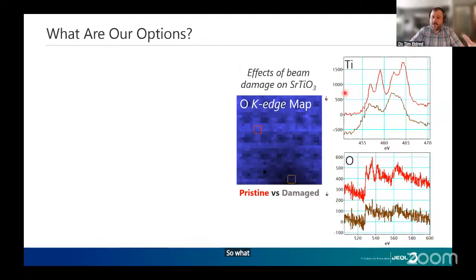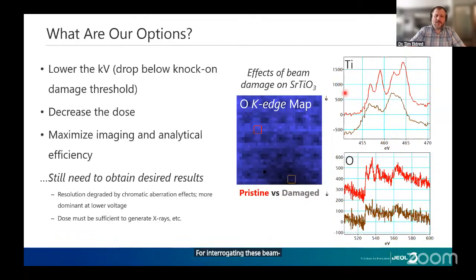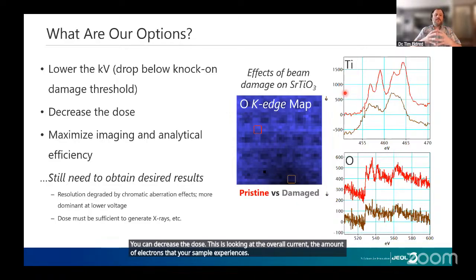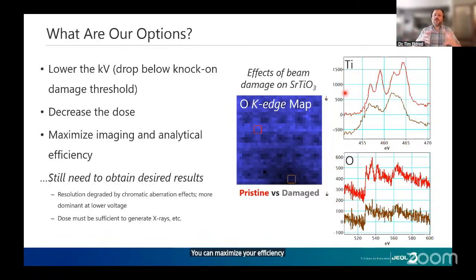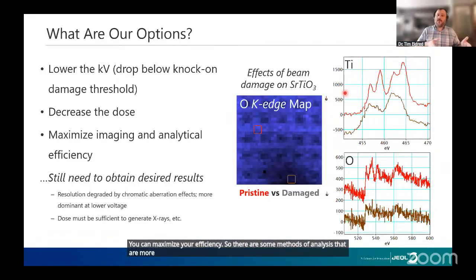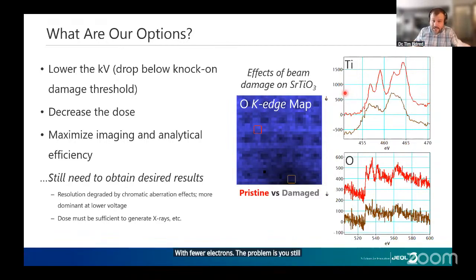So what are our options for interrogating these beam sensitive materials? Traditionally, you would lower the potential of the gun. So you can imagine if you have a lower energy electron beam, you would cause less knock-on damage, where you're literally knocking atoms out of your system. You can decrease the dose. This is looking at the overall current, the amount of electrons that your sample experiences. You can maximize your efficiency. So there are some methods of analysis that are more dose efficient, so you can get the same information with fewer electrons. The problem is you still need to get the data. You still need to get the data to draw the conclusions. You can't answer the question without the data.